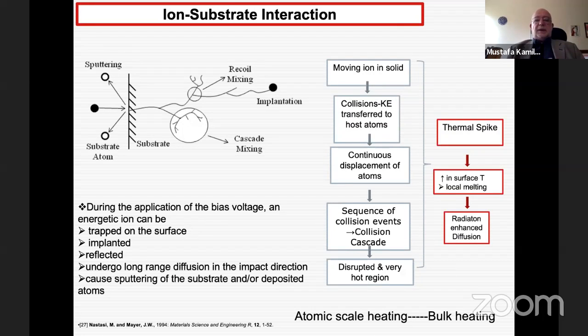So what happens when the ions and substrates interact? Lots of things happen. Sputtering happens, recoil mixing happens, implantation happens, and all of these processes result in local heating of the substrate material, which in turn may lead to local melting. And overall, we go from atomic scale heating to bulk heating. So when I apply a voltage to the surface of my substrate, then I can have an additional effect that can be created by the application of this bias. This is heating.